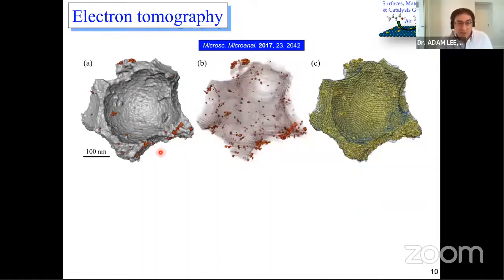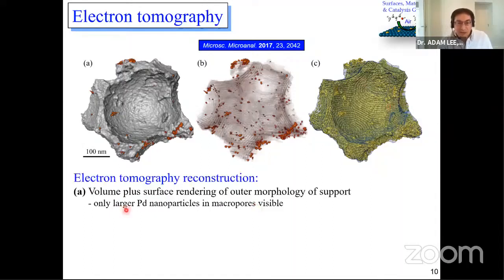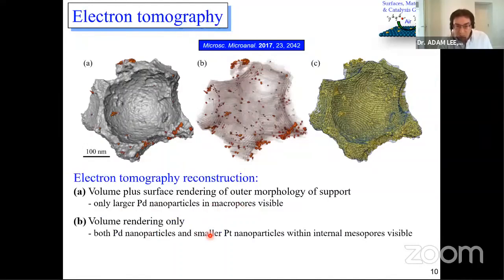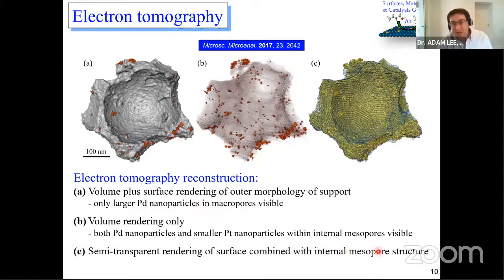So what we can do is that if we look at just the surface of the macropores, we see only large particles. These are palladium. If we make the surface semi-transparent, you can now start to see these small particles appearing. These are platinum nanoparticles, and you can even see the pore network itself. So these are the mesopore channels that are decorating the outside of a large macropore. So we can see that we have palladium nanoparticles in the large macropores. That's here. We can see smaller platinum nanoparticles just in these mesopores, so in these smaller channels. And we have the ability to image the individual structure.